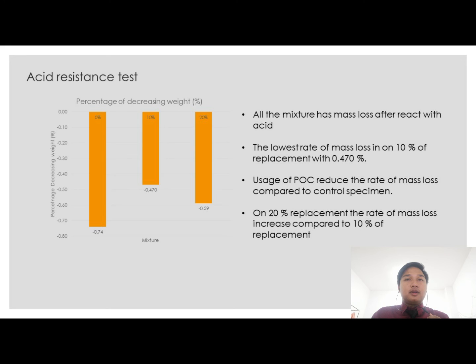This graph shows the percentage of decreasing weight. All the mixtures have mass loss after reacting with acid. The lowest rate of mass loss is at 10% replacement with 0.470 percent decrease of weight. It's good compared to normal concrete because the normal concrete recorded the highest percentage of decreasing weight with 0.740.